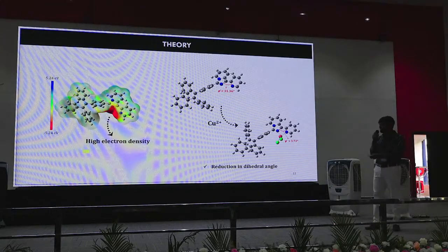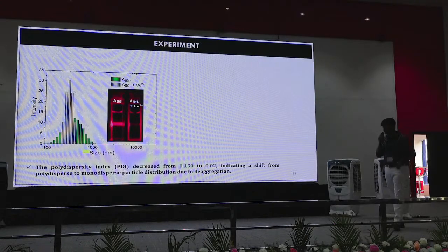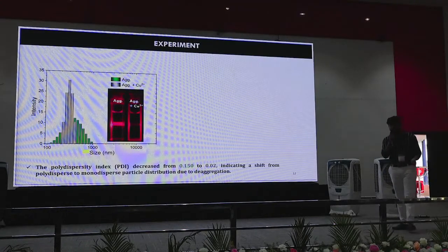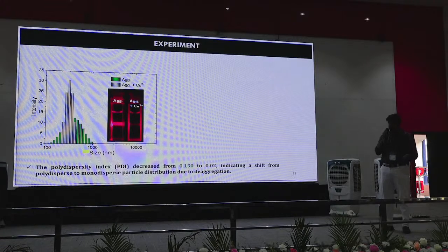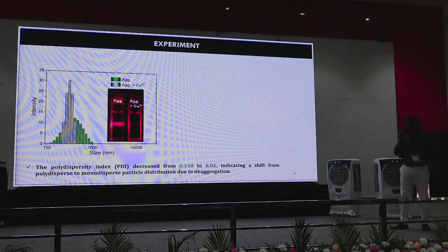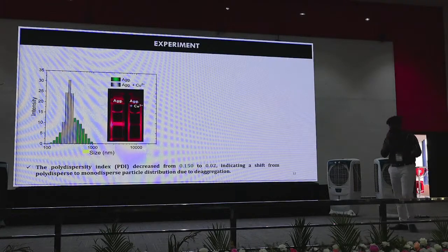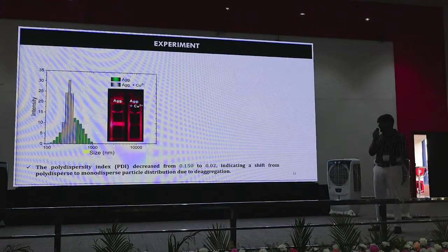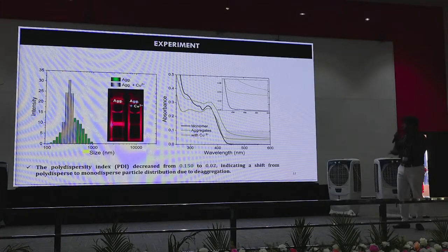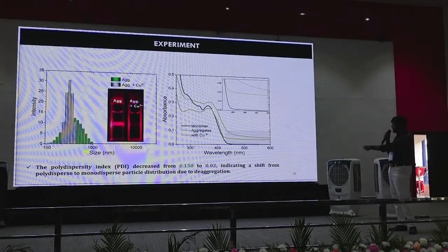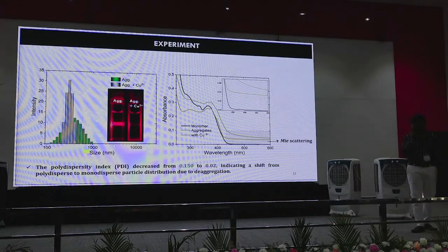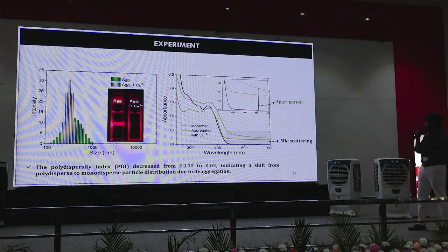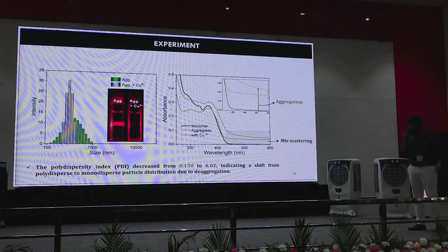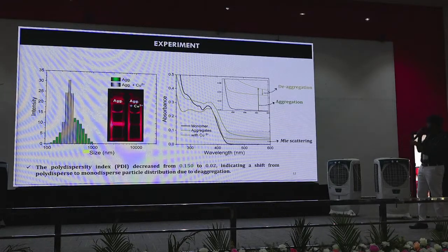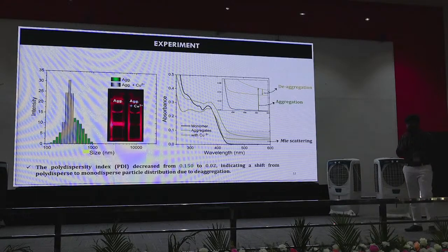So we did experiments, and the experimental evidence is shown here in the DLS. The polydispersity index confirms whether the molecule is monodispersed or polydispersed. As you can see here, when the copper is introduced into the aggregates, the polydispersity is decreased, thereby proving complexation. And we also did spectroscopic characterization, wherein this is called Mie scattering. Photophysicists might know this. In Mie scattering, when the aggregates are formed from the monomer, there is Mie scattering. So when copper is added, there is a reduction in the Mie scattering. So this is also one of the proofs which supports our claim.